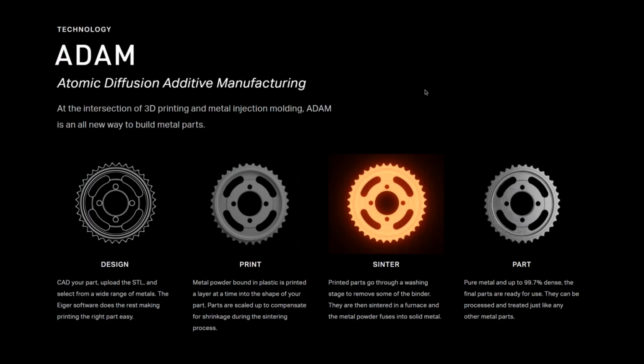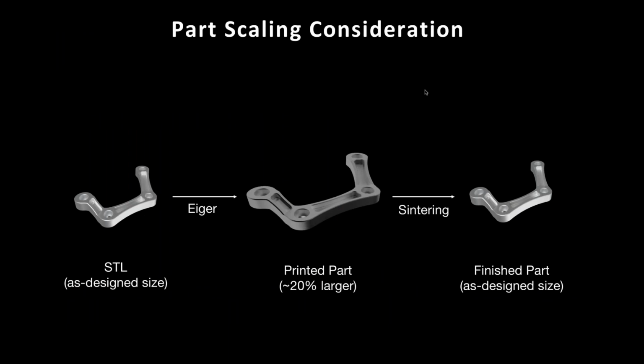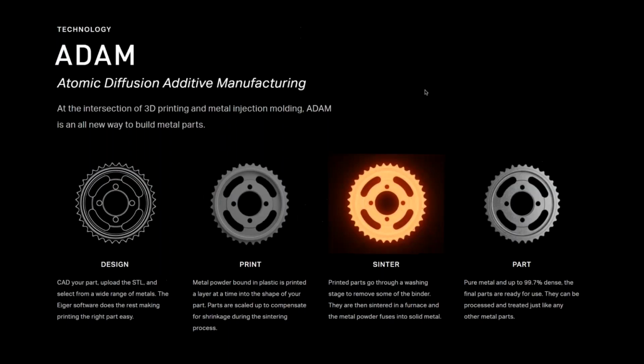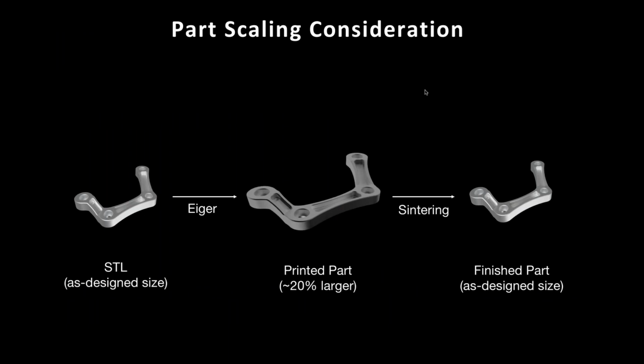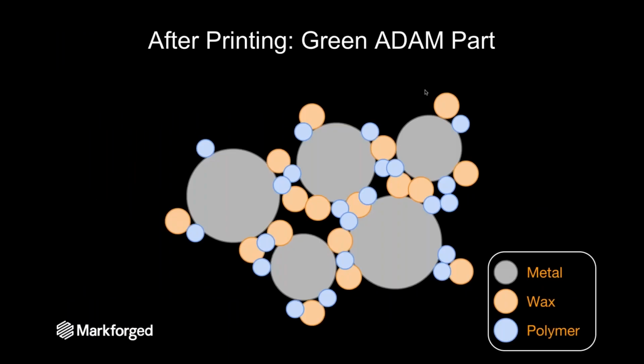Our process is called ADAM, Atomic Diffusion Additive Manufacturing, and you put your design, your STL file, into our Eiger software. Our software will automatically scale it up about 20%. This allows us to account for shrinkage that's going to happen during the sintering process. Then it goes into a wash to remove the wax portion of the binder and the sinter to remove the polymer portion of the binder, as well as to create your fully dense part. So you design your part that you want to come out, and then our software will automatically scale that up for you. So what does this look like?